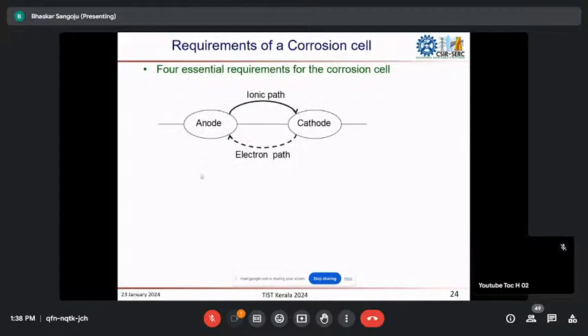So there are four essential requirements for a corrosion cell or corrosion to continue. That is anodic formation, cathodic formation, and a combination of this anodic and cathodic sides. So that means coupling of the anode and cathodic side. Here, as I said, electrons and ions. Ions will be available in the pore water, whereas electrons means through the metal. So if there is a coupling or continuity or connectivity between anode and cathode, and presence of oxygen and moisture, the corrosion process will continue. Otherwise, there will not be any corrosion.